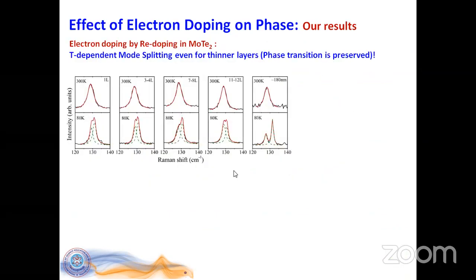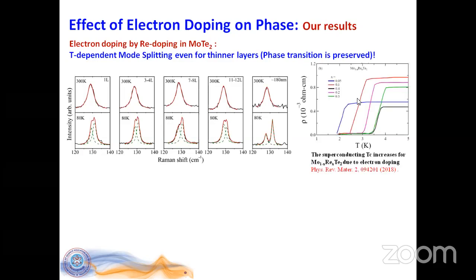Now we also did another way of electron doping, which is rhenium incorporation into the molybdenum sites, and that gives electrons to the system, and also lattice strain, and it will have some other effects as well. But let's see what our observation is. We experimented from very thick down to monolayer, and we still see a very clean splitting of this mode into two. That again establishes the phase transition, even down to a monolayer.